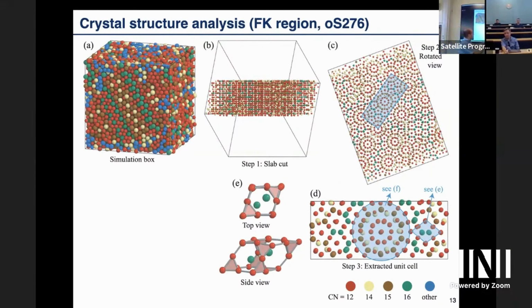The center part is a Frank-Kasper polyhedra, and these red ones are tetrahedra. You can in principle take this as a tile, and then when you take this rhomb, you can tile it periodically, and you get one type of Laves phase, I think the C15, and if you do it alternatingly, you get a C14.